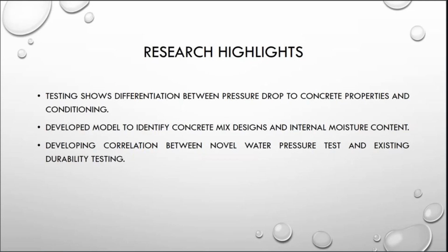In terms of moisture content, we are seeing that there is different behavior when the concrete is wet or when it's dry. Both show different things, but very interesting. You can try to get a difference in the concrete material itself. So when we start doing some trials in the field, we're thinking of evaluating the systems when it's wet and when it's dry. And that can be done in a practical sense too.